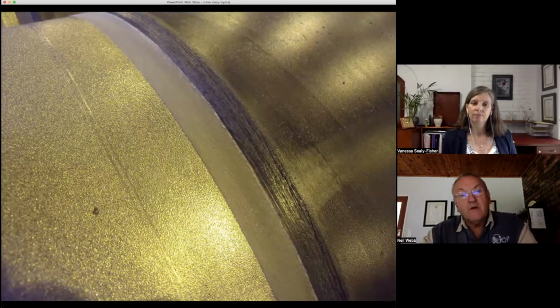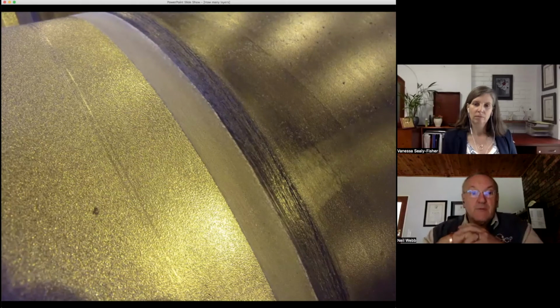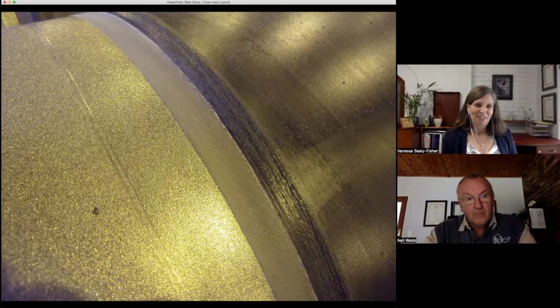And in order to achieve that, a lot of the pipe mills now use a phosphoric acid-based wash as a pre-treatment for the application of fusion bonded epoxy. And there has also been other chemical treatment, notably chromate treatment, which has been given the black flag by the environmental lobby. And it's unfortunate because a chromate treated pipe, or chromate pre-treated pipe, actually has absolutely outstanding corrosion resistance properties with a fusion bonded epoxy coating on it. And the industry really has to jump through hoops in order to compensate for the lack of that chromate. Sadly, that's often the case, but all of those